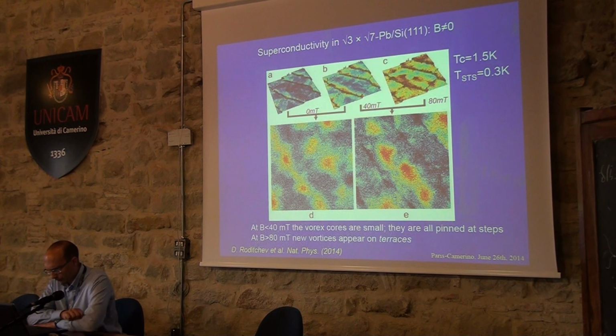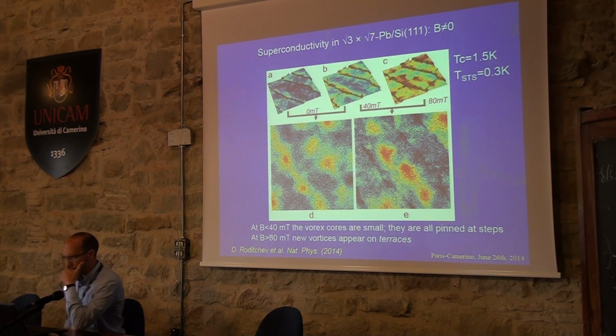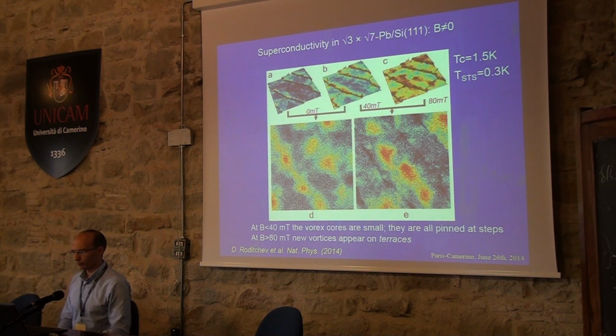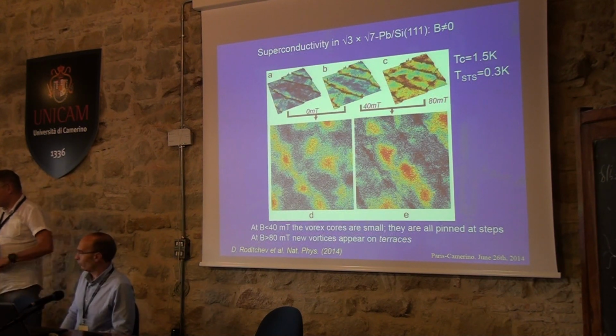So each line here, there are 4 lines, each line is a single atomic step. If you raise the magnetic field, you will get additional suppression of the superconducting order. Now, if you subtract map A from map B, you will get the map here, in the bottom left part, and you will see that all atomic steps are decorated with vortices. All of them. And, yes, I'm almost done. This is my last slide.